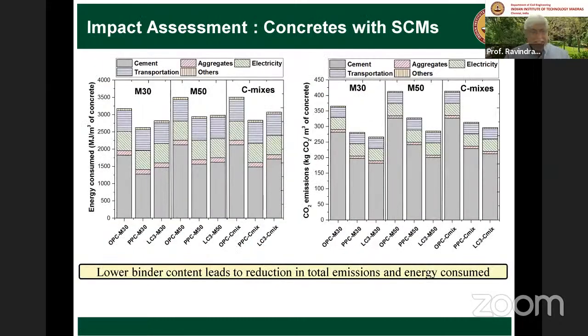These can be used at the sites. So I'll show you some results. On the left, you have the energy consumed. On the right, you have the CO2. And clearly you see that if you compare with OPC, PPC and LC3 are coming out much, much better in terms of energy as well as carbon dioxide. There is a slight increase as you increase the grade, but that is okay because you'll use less amount of M50 anyway. So clearly what benefit we see in the cement is also there in the concrete.